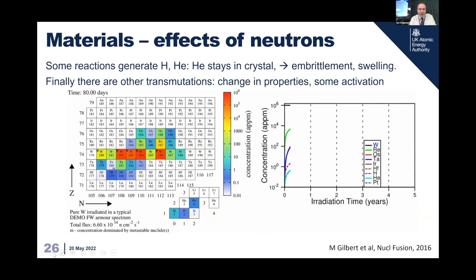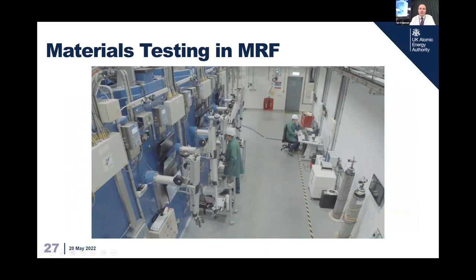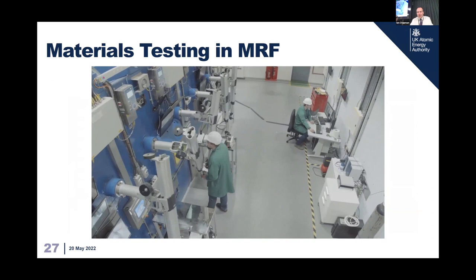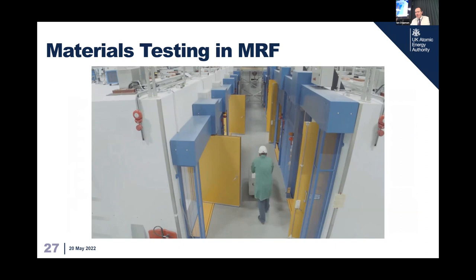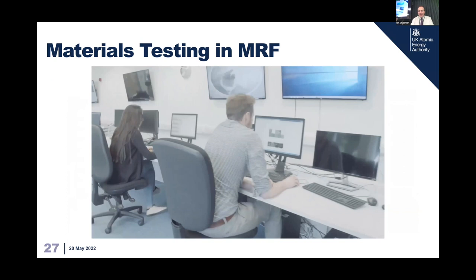We are, however, doing some testing. So a few years ago, we built this facility. It's called the Materials Research Facility, where we can put structural material, so steel or tungsten, things in test reactors. Now, those test reactors are either low energy, high fluence, I mean, fission reactors, basically, or high energy, low fluence. So there's no way of replicating the high energy, high fluence. But we can test components. We then put them through our hot cells, cut them up into small samples, and then do micromechanical tests.